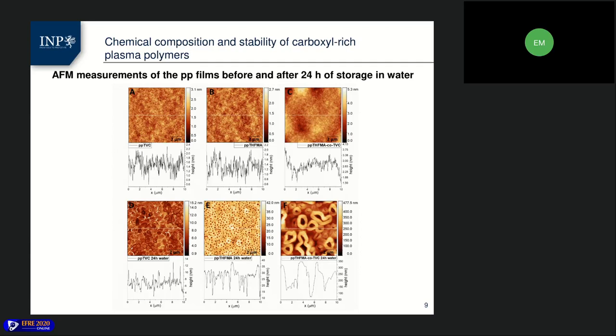And the copolymer exhibited morphological changes that represented the sum of the rings and pinholes, which were the large donut-like structures that were found all over the surface of these films. These dramatic changes resulted in an increase of surface area by about 15%. And generally, the increased total surface area can be beneficial for more efficient immobilization of biomolecules.